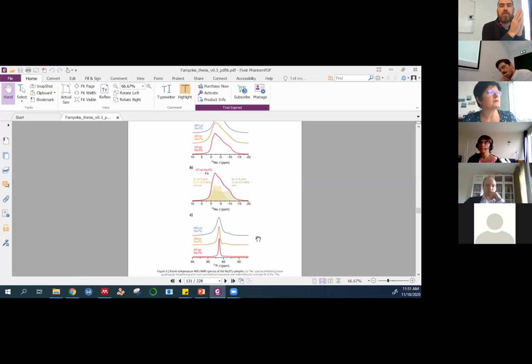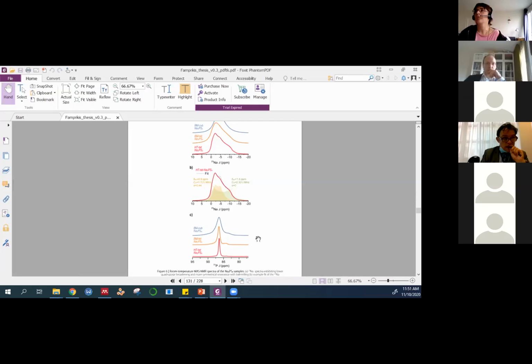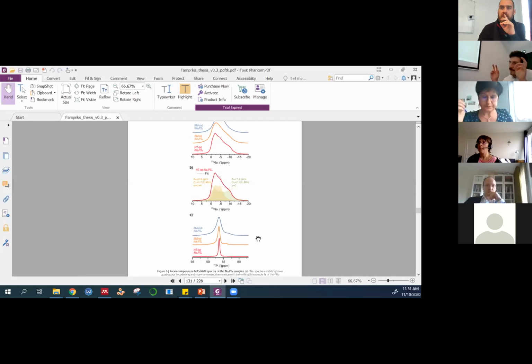Yeah, but in that case, considering your structure, it means a significant modification of the local structure, because your tetrahedra are... Yes, I'm not sure if the fact that I see it in NMR means that I should really have significant concentrations of them in my bulk. I agree that around such a defect, there would be significant modification to the structure, in the sense that it would not contribute to the Bragg diffraction. You would simply have an amorphous background associated with that phase. So the fact that I have no signal from diffraction that points to that is not necessarily to say that they don't exist.